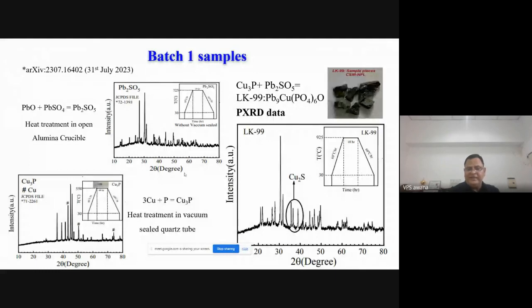In that sense, after looking at their results, we did our own studies and started the sample immediately after 22nd of July. On 31st, our first arXiv paper came in the literature, and that was like you have to make Cu3P and Pb2SO5 to lead to LK99. Our first Pb2SO5, as you can see in the panel, was good enough, but when we had Cu3P, we had some copper peaks which are identified here. Then we got lead to LK99. This was the first sample of ours. We started on the same day, 22nd July, and we found that there is a good amount of copper sulfide, which was there in the LK99 of the Korean sample as well.